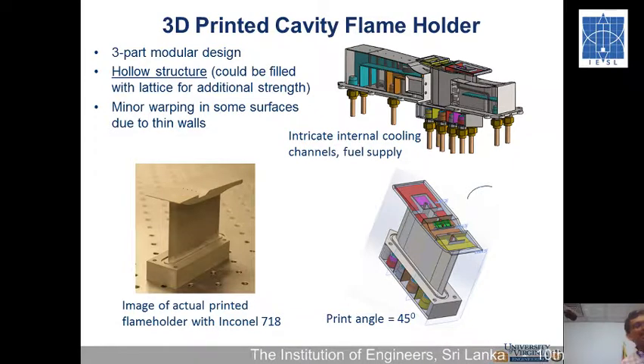1.25 millimeter thick shell essentially. And by doing that, we are able to take the powder out, and we get all the flow rate that we needed. Okay.